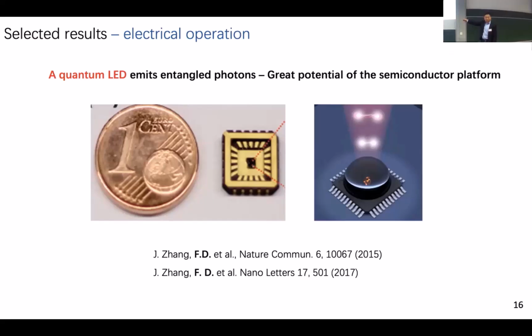Of course, we have to do wire bonding. The semiconductor quantum dot is embedded in a p-doped layer, n-doped layer, and the intrinsic layer is the quantum dot, okay? When we give a few volts, which means you can operate it by just a battery, the quantum dot will emit single photons and entangled photons. Of course, I still have to mention why we need a piezo here. Because the quantum dot is intrinsically not able to emit entangled photons. In the past, people tried to look for the so-called hero quantum dot. They looked through thousands of quantum dots, and finally found one which is able to emit entangled photons. That's not good. So today we know that you always need some tuning knob. It can be strain, as we use here, or an electric field, or many other possibilities.